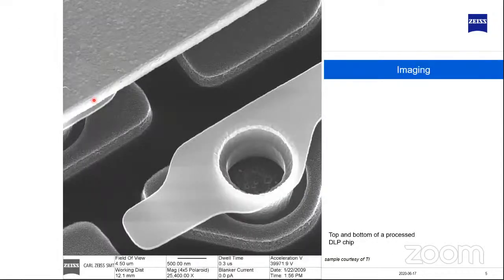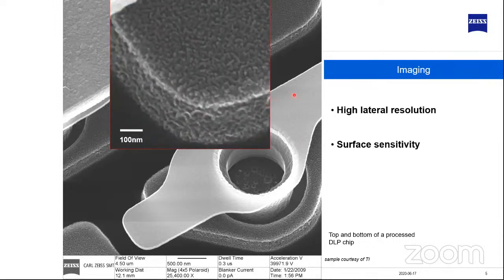Okay, what do images look like that we take with this type of system? First of all, they look very similar to an electron microscope image. The reason is simple. We're rastering a beam over the sample. We're collecting secondary electrons, and that generates a raster image. But now if we look a little bit closer to that, we see some differences. Number one, we see an excellent, good lateral resolution. We see a very, very good surface sensitivity.